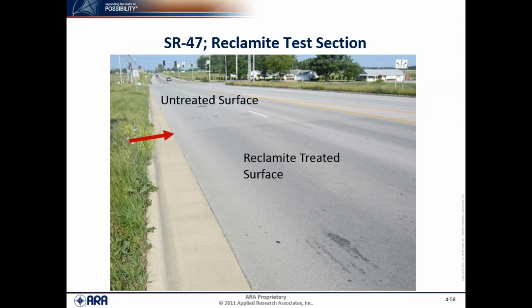The other thing that we saw for all of the Reclamite sections, you can see here, this is on State Route 47, and this was true for all projects. You can see where that paper was laid out, and there's a very distinct difference in the color. Really, the Reclamite sections were easier to find because of the color difference. You could still see that the treated section had a different color to it.